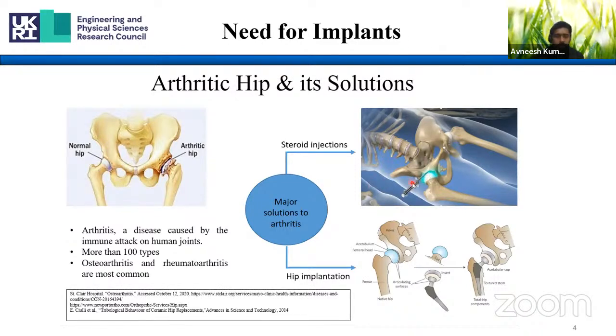But the problem with this injection is that its life is very short, maybe around 3 to 4 months maximum, and this injection doesn't work for every patient. Also, this injection therapy is very painful. On the other hand, we have implantation surgeries. For example, for a hip implant, the cost of one implant surgery is around 3,000 US dollars, while the cost for one steroid injection therapy is around 400-500 USD. The life of these implants is around 10 to 15 years.